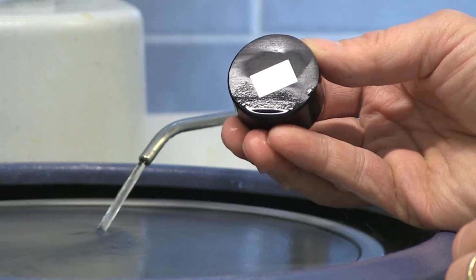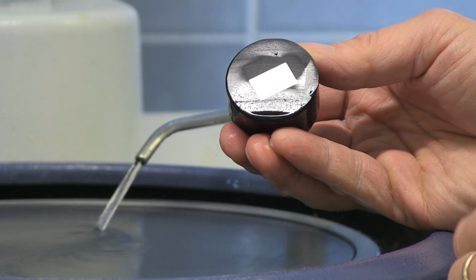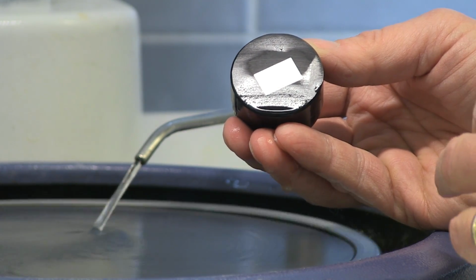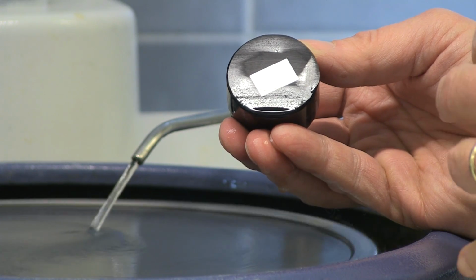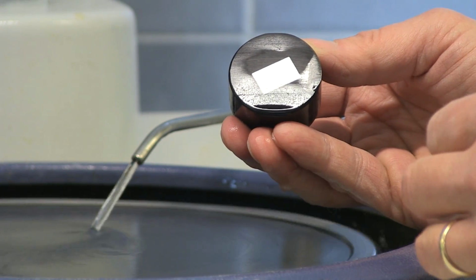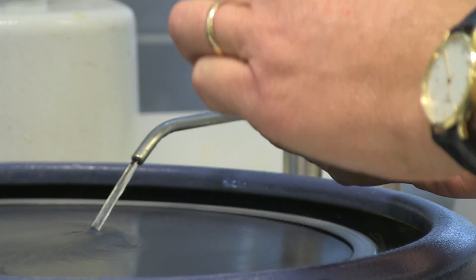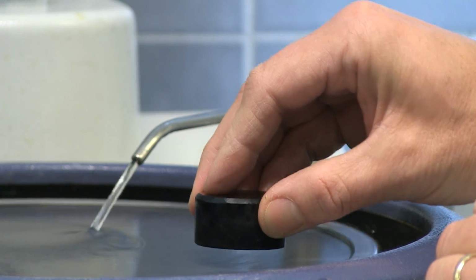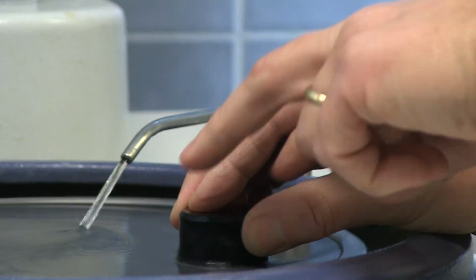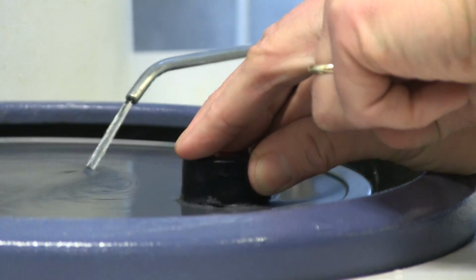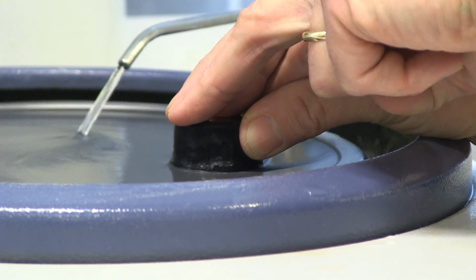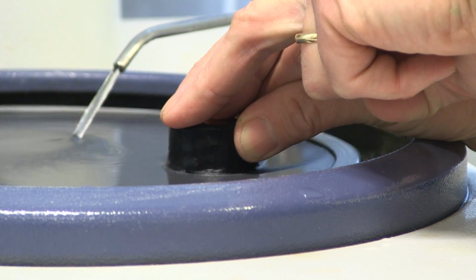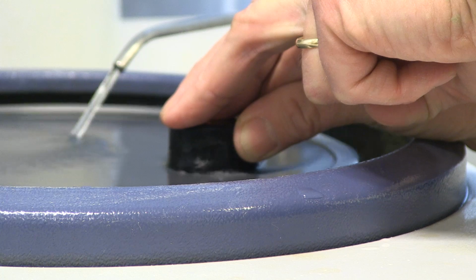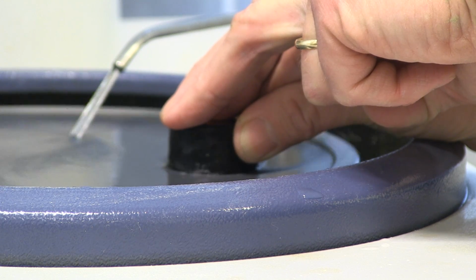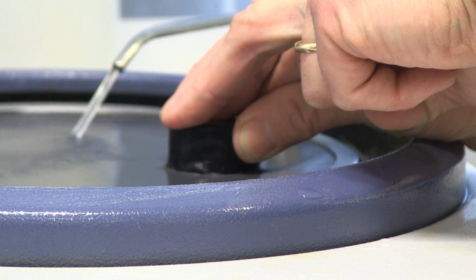The reason for that is that if I do that, it's much easier to see when old scratches are removed and new scratches are introduced. So I start now and I put the sample down, and usually I hold with both hands, and I concentrate much more on holding it flat than pressing on the sample. I have some pressure on, but I concentrate more on holding it flat.